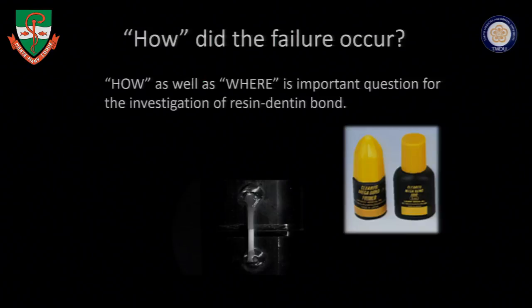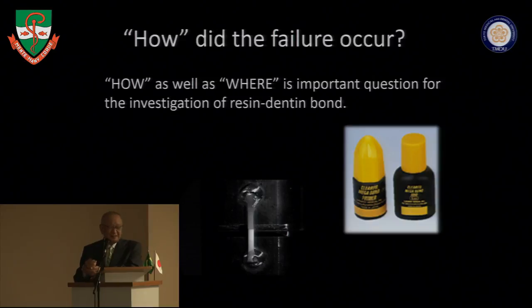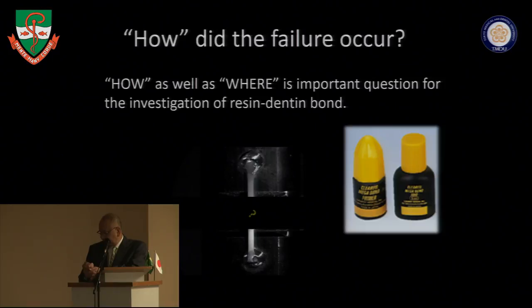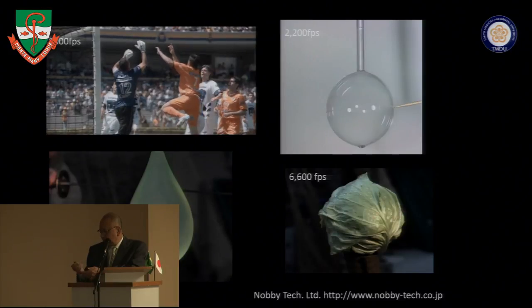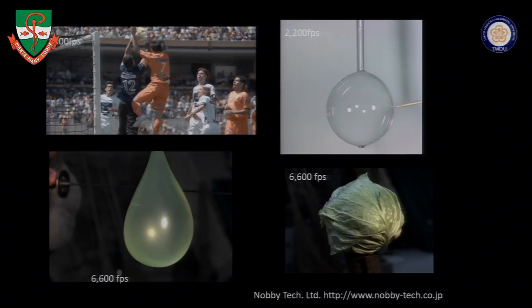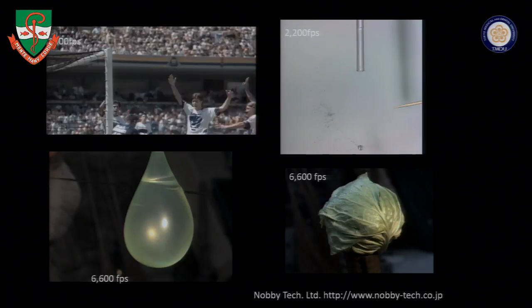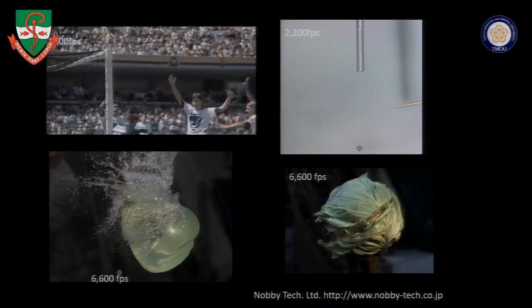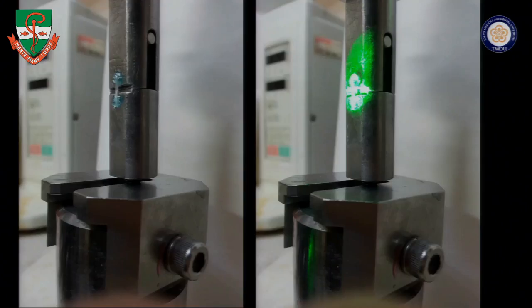To analyze that weak point, we try to observe the initiation of the fracture during the bond test. And we try to observe under high-speed recording. This is 1,000 frames per second, and 2,200, 6,600. Like this. So beautiful movie. And we try to observe the bond test with high-speed recording. This is the specimen for the microtensile test for bonding evaluation.